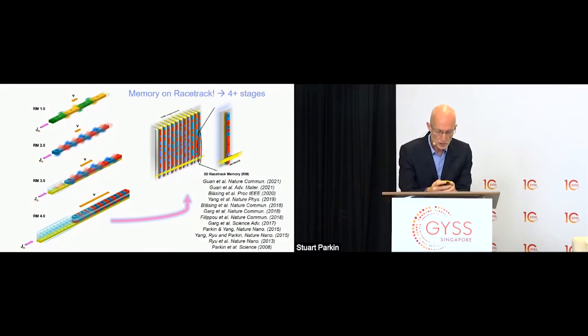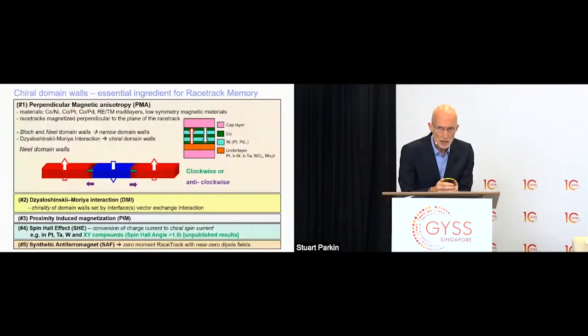I first proposed 25 years ago for spin valves to eliminate the dipole fields. And it turns out that's also super important in racetrack because the dipole fields emanating from one magnetic region to another will cause interactions both within and between distinct racetracks. I want to briefly discuss that in a moment. So there are essentially four or five important ingredients to make this racetrack work.